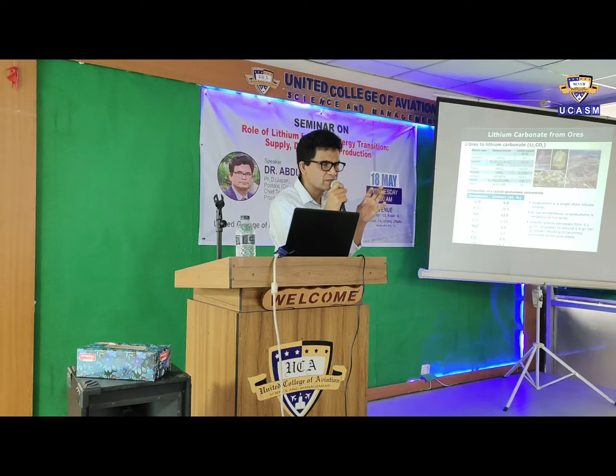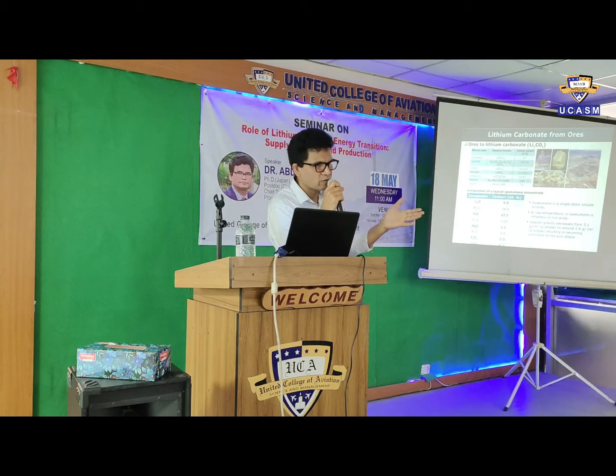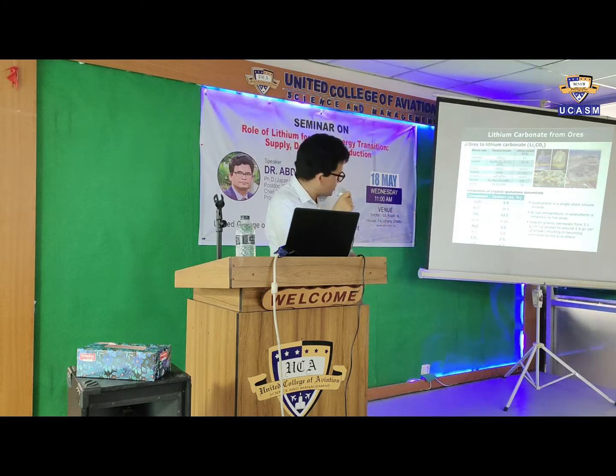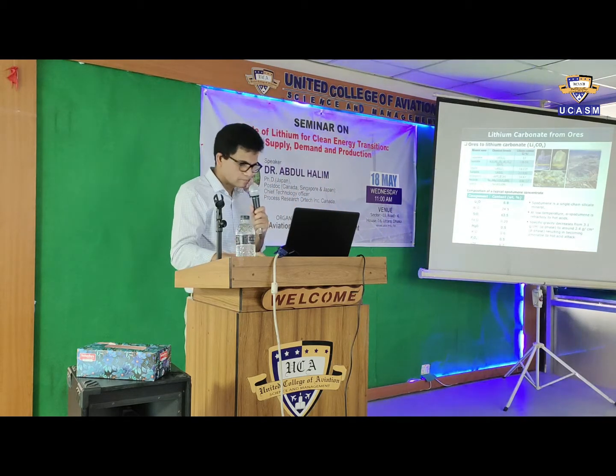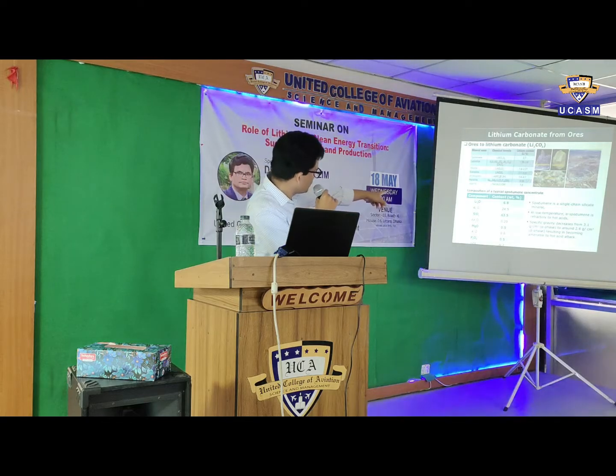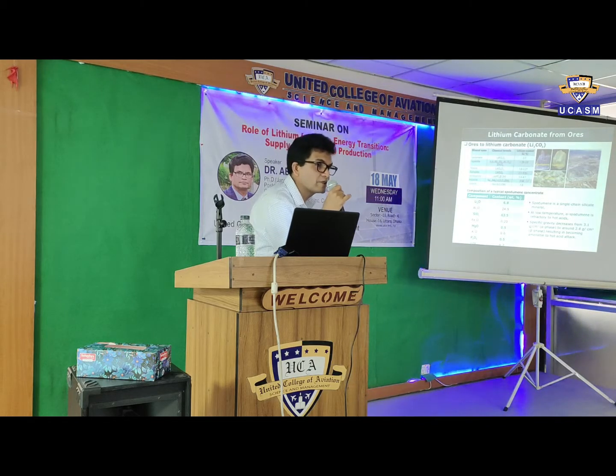So initially this mineral is in the form of alpha. We call it alpha spodumene. The density is high. What we do is convert it from refractory to non-refractory mineral by doing treatments that I will discuss later. You can see here the concentration of lithium oxide. It is 6.8%. That is after doing the mineral processing. But in the beginning it is around 1%.